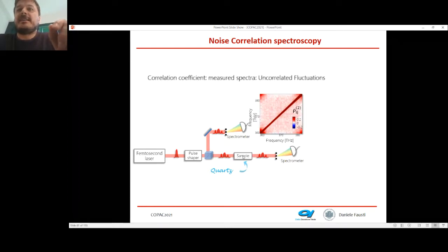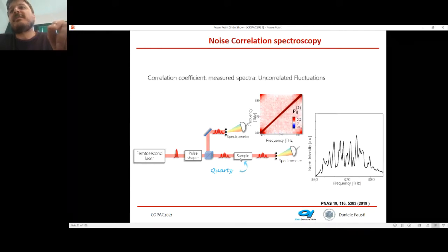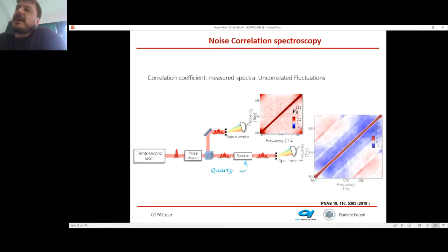Now I use the same set of data, which I split by a beam splitter. I make them interact with a sample, and you see immediately that, again, I don't see much if I look at the pulses, because I do have random fluctuations. But if I do the correlations, I see that I immediately develop correlations which correspond to the Raman response of my material. So I introduce correlations between frequencies which differ by the Raman mode of the material.